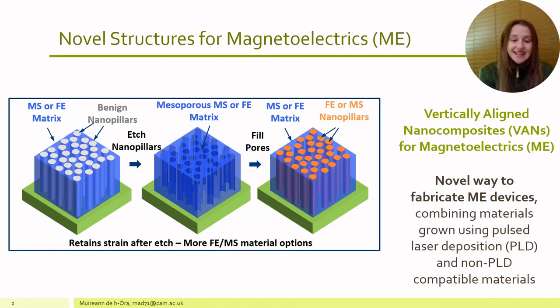My PhD focused on novel structures for magnetoelectrics, and specifically vertically aligned nanocomposites. I first started with a VAN film of a ferroelectric or magnetostrictive matrix with nanopillars embedded. I had to etch these nanopillars away, and then I can fill that with ferroelectric or magnetostrictive nanopillars. This is just a novel way to fabricate magnetoelectric devices, combining materials that are typically grown using pulsed laser deposition, or PLD, and non-PLD compatible materials.